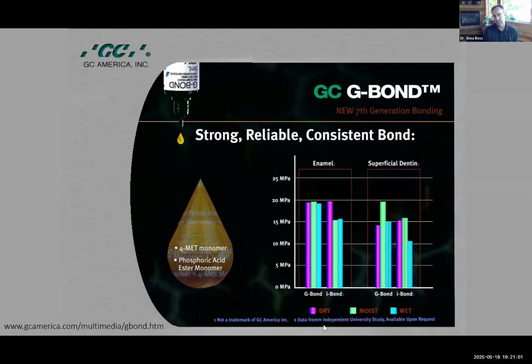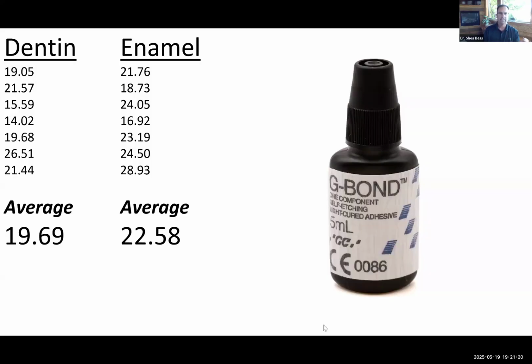So I looked at their website, and you can see they say to dentin, you can expect somewhere around 20 MPa if you're bonding to moist dentin, and somewhere in the 20 MPa if you're bonding to enamel. So I took 7 specimens of dentin and 7 specimens of enamel, and sure enough, right about 20 MPa.